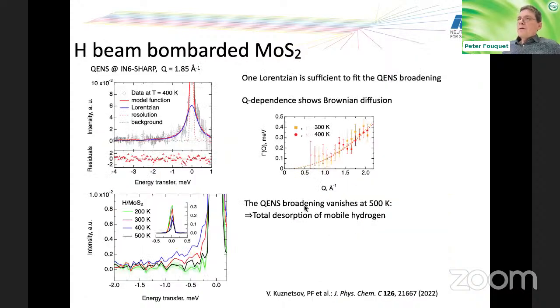Now with the quasi-elastic signal, we see a bigger broadening than what we saw for the water-soaked samples. And here we interpret what we see as a diffusion of hydrogen ions. And we can also follow how, with temperature, this hydrogen desorbs. Basically a total desorption of the mobile hydrogen by 500 Kelvin.